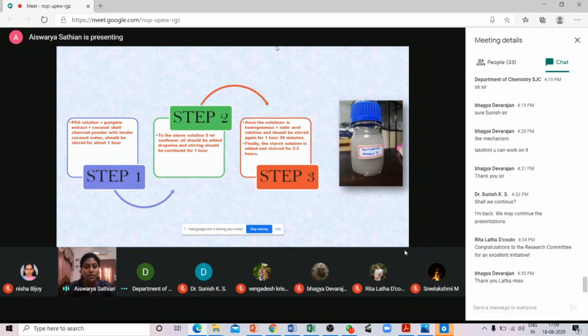I kept it for stirring for about 1 hour. I used a mechanical stirrer at an RPM of 1500. To the solution, I added sunflower oil dropwise and then I again stirred it for 1 hour. In the final stage, I added the oleic acid and also the starch solution and kept the whole solution stirring for 2 to 3 hours. Then in the final step, I got the solution which is shown on the right side of the screen.